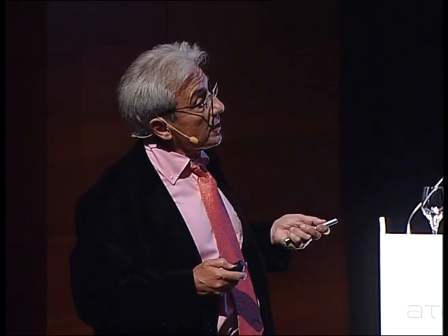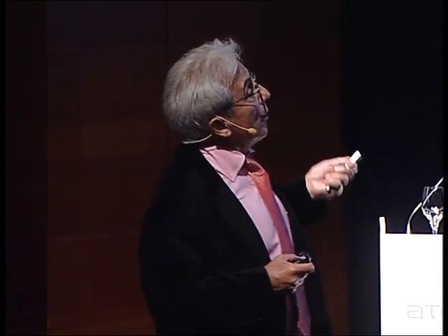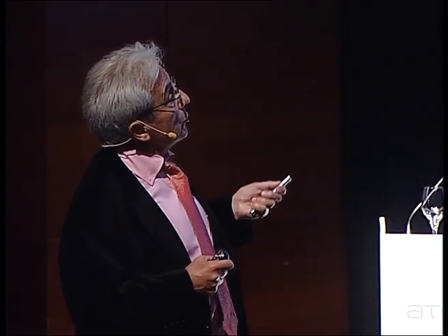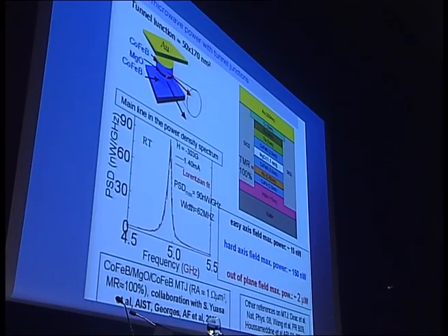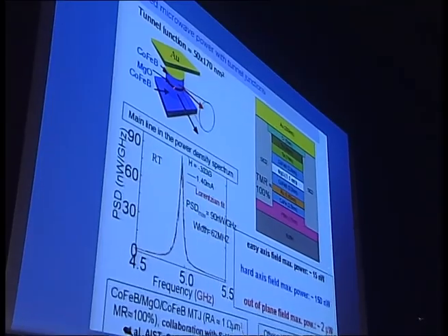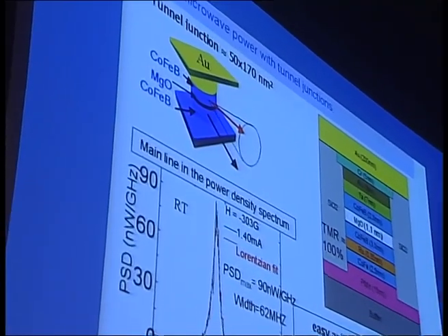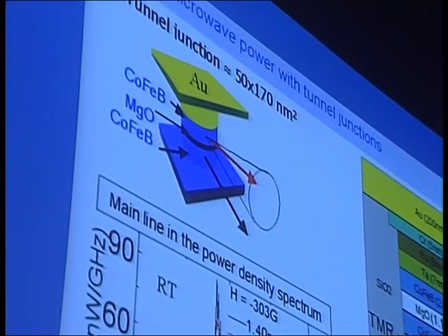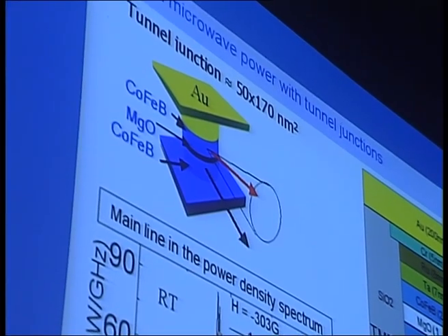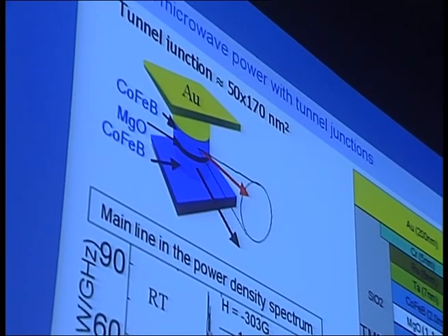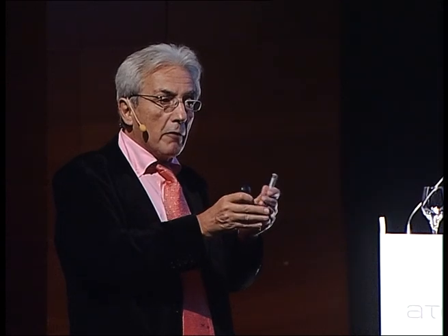I want to discuss how to increase the power of these STOs, these spin transfer oscillators. First, to proceed from metallic structures to tunnel junctions, especially tunnel junctions with the MgO barrier, which have a very large magnetoresistance. Of course, with the large resistance of the tunnel junction and also the large magnetoresistance, the periodic variation of resistance as a function of the angle becomes very large, the voltage becomes very large, and the power can be increased significantly.